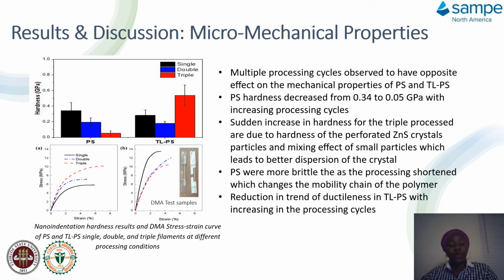And when we check to confirm with DMA results, DMA also shows that as the multiple processing cycle increases for pure polystyrene, it becomes more brittle. So from the 1st extrusion to the 3rd extrusion, it becomes more brittle. So triple extrusion is more brittle than the 1st